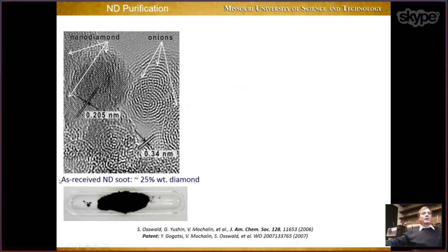When you get nanodiamond from detonation reactor, this is how it looks like. So it's black. Why is it black? Because it has a lot of non-diamond carbon. If you put it under transmission electron microscope, you will see that there are diamond particles here and there, but the majority of material is made of non-diamond carbon. Mainly carbon onions shown here, also amorphous carbon here. So all this needs to be removed if you want to work with nanodiamond.